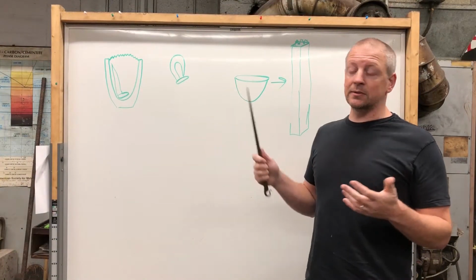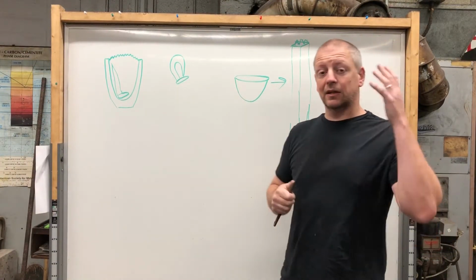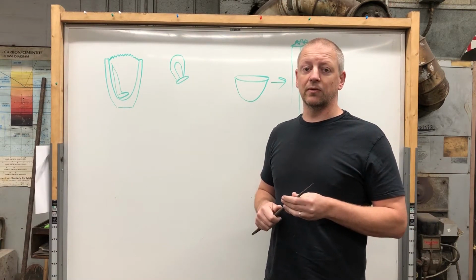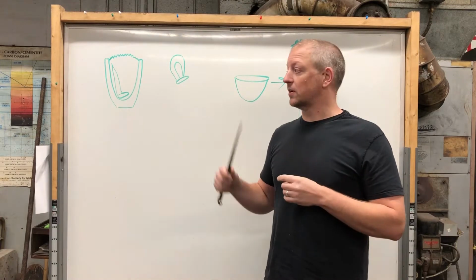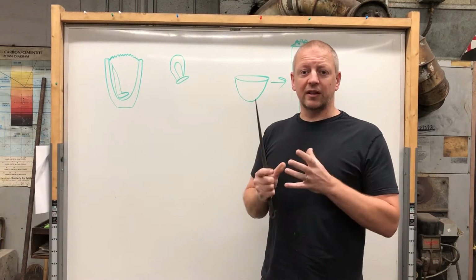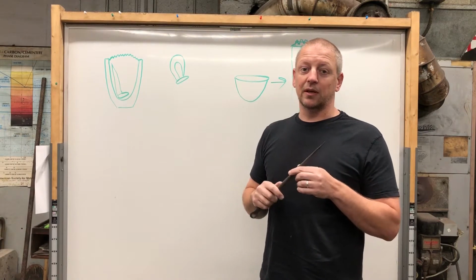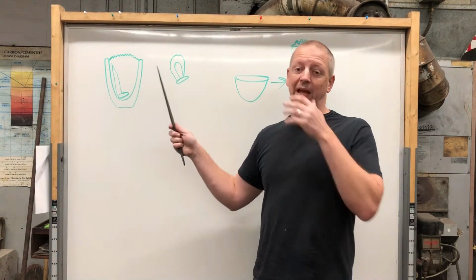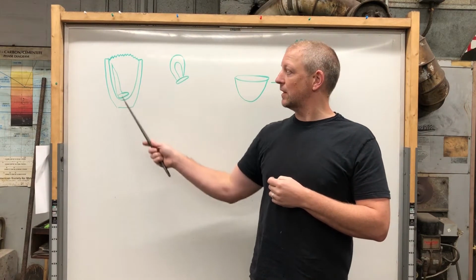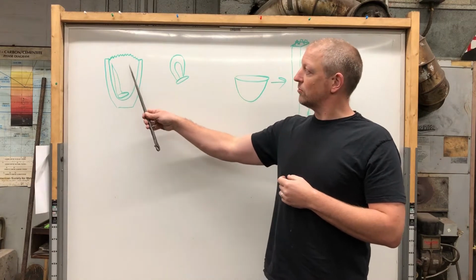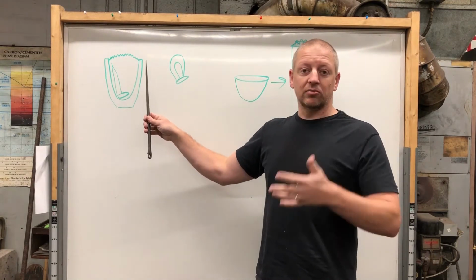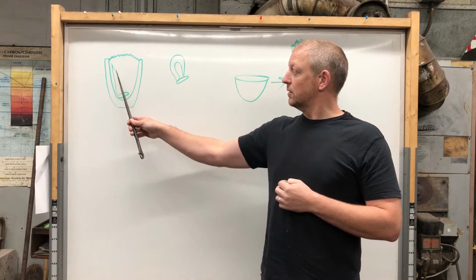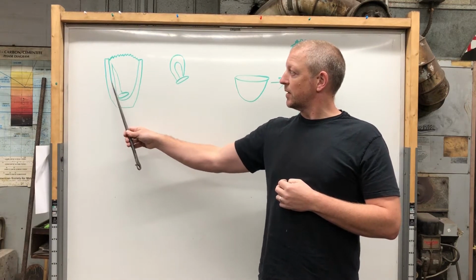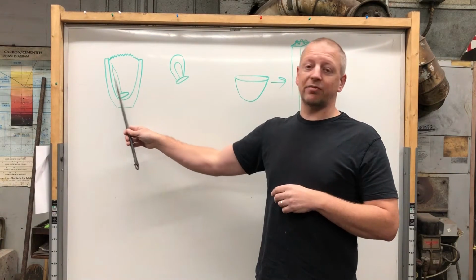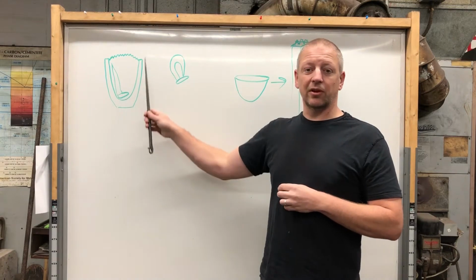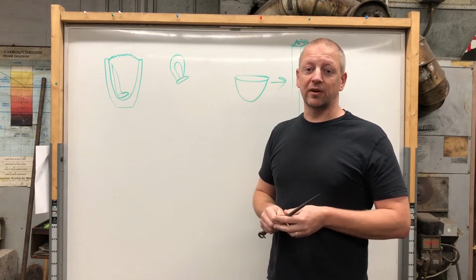Before I got to this nice solid ingot, and I've got some stills of that, which I think will get interspersed in here, I got a kind of crappy ingot. The reason for that was A, all that oxide at the beginning, and B, the height of these. As soon as my glass melted and my small cast iron constituent melted, I think my actual liquid level was about halfway up the crucible, leaving the ends of all those just protruding up into the furnace atmosphere.